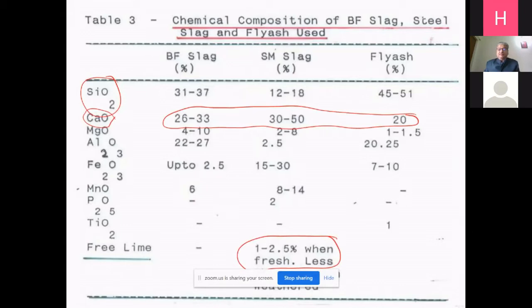This free lime, when used in road construction, reacts with the moisture in the environment, and because of that swelling takes place, and due to swelling there are cracks and volume change. So it was thought, what to do with this material, because after construction there were cracks initially.